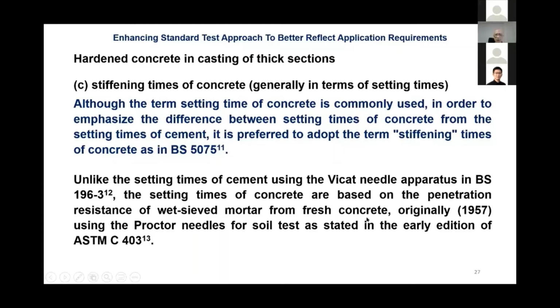Unlike the setting time of cement, which uses a Vicat needle, I wonder how many of our students still remember what the Vicat needle looked like. But these days, we don't make them do the lab, so maybe they're not even familiar with the difference between the Vicat needle and what we are doing in the setting time. Another thing that we can notice is that because the original test used equipment based on soil tests, which I'll come back to, they cannot test with the full 20 mm aggregate. So they wet-sift the mortar fraction and test. So that is further moving away from real life, which is concrete.